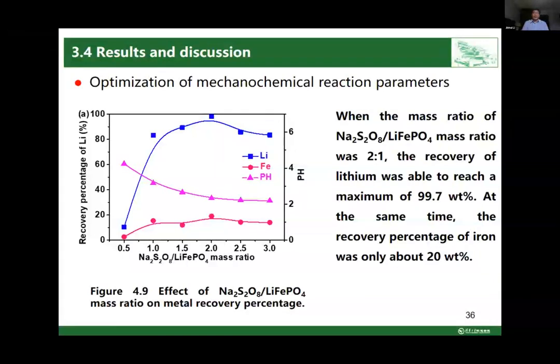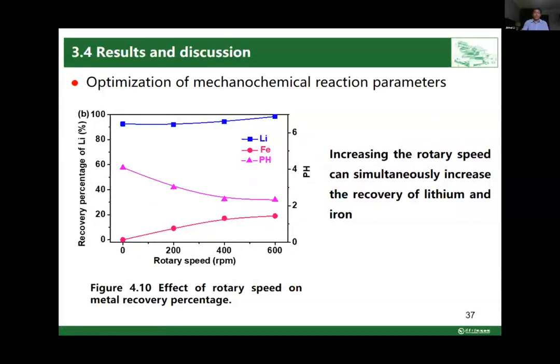So this shows the effect of different sodium persulfate/lithium iron phosphate mass ratio on metal recovery. When the mass ratio is 2 to 1, the recovery of lithium was able to reach a maximum of more than 99%. At the same time, the recovery percentage of iron is only about 20%. So the result of this figure shows that increasing the rotary speed can simultaneously increase the recovery of lithium and iron, but the effect on iron was significantly higher than that for lithium.